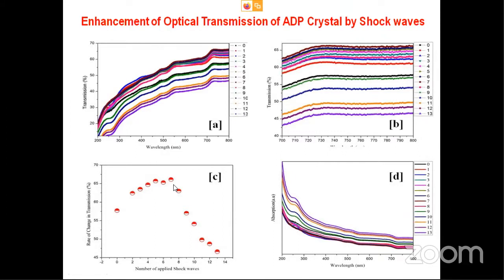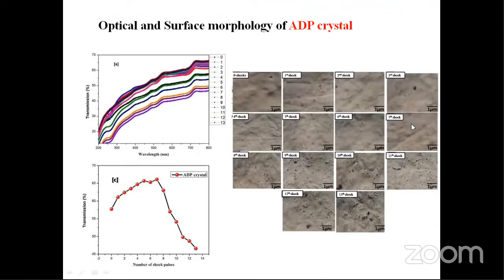Why is it going down? When the shock wave hits the surface of the material, it slowly damages the surface. Though the crystallinity is improving, the surface is slowly damaging. Therefore, the incident light is scattered, and the resultant transparency slowly decreases. This is the example, as I told you. You can see the micrograph of the surface of the crystal. This is the control. First, second, third, fourth, fifth, sixth. After 6, you can see some defects. Slowly, the defects increase. That's why after some number of pulses, the transparency slowly decreases. Though the crystallinity increases, the transparency decreases.